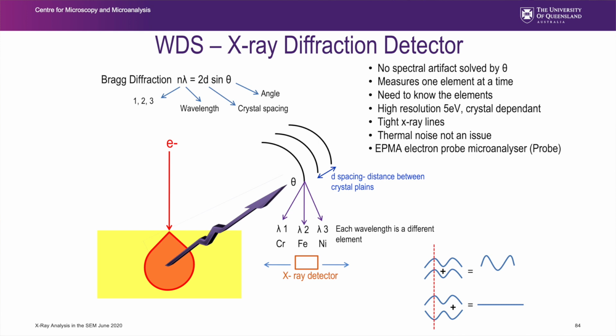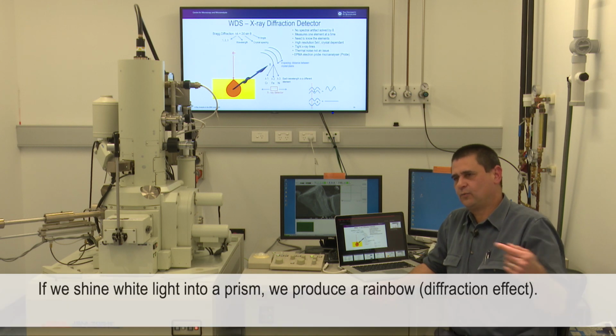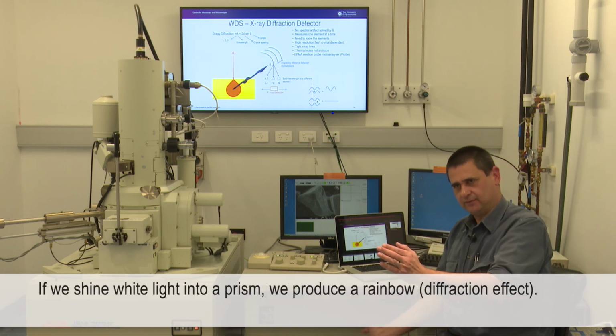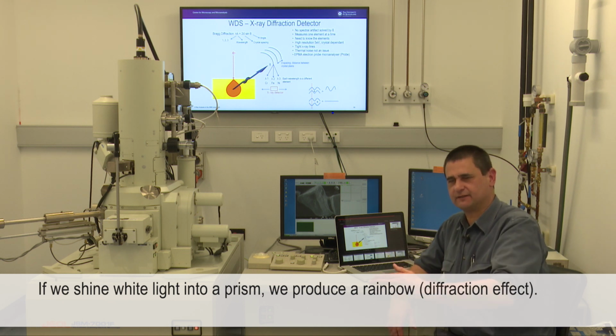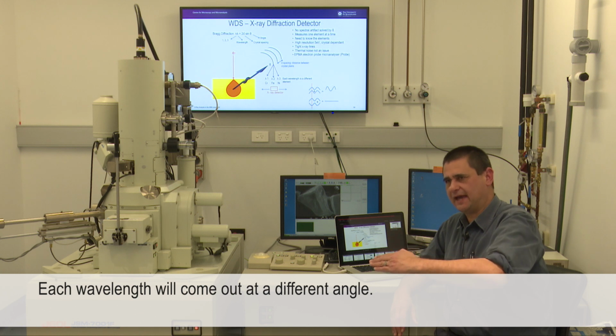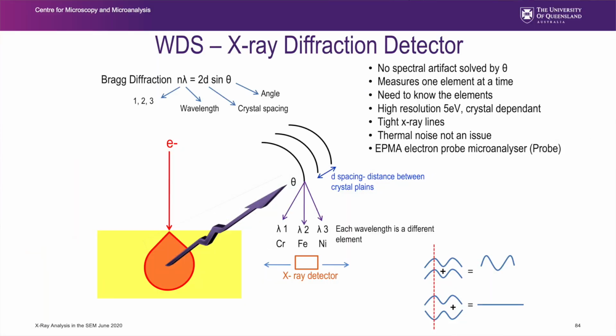Let's now talk about a WDS detector, a wavelength dispersive spectrometer, traditionally fitted to a microprobe. But I have fitted them to SEMs for various reasons. We have the Bragg diffraction law, n lambda equals 2d sine theta, where n is the order of diffraction, lambda is the wavelength of the X-ray, d is the d spacing between the atomic planes of the diffracting crystal, and theta is the angle that they come out at. Effectively, we all know that if you shine white light into a prism, we get a rainbow coming out of it. That rainbow is a diffraction effect. Each wavelength will come out at a different angle. And the same thing happens with my diffracting crystals.